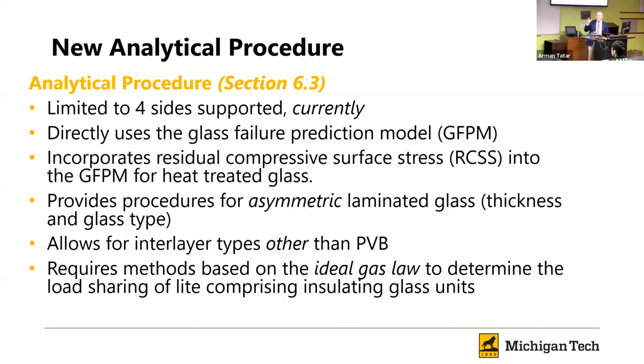The charts for laminated glass were based on symmetric laminated glass, which means that both plies were the same thickness. There's various reasons why somebody might want to make those different, and so we provide the keys, if you will, the methodology to take advantage of that. Also, it incorporates the ability to use interlayers other than PVB. Most notably, and pretty popular in the industry right now, are ionomer-based interlayers, which tend to be quite a bit stiffer. But there are also stiffer PVB interlayers on the market as well. But currently the charts just have the regular one, all right?